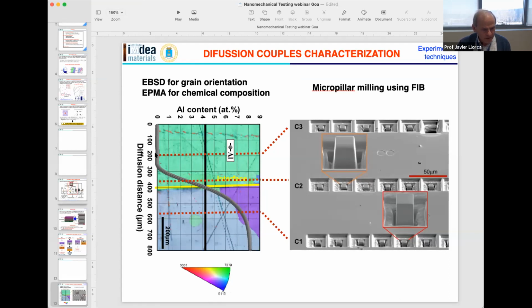And as you move from here to here, what you are doing is increasing the aluminum content. So at this point, the aluminum content is practically 0. This is pure magnesium. And as you move here, you are increasing the aluminum content up to 9%. If you carve micropillars along this line, you can see these nice micropillars produced by focused ion beam milling. This micropillar will have a magnesium content that is 100% and 0 aluminum. This micropillar here will have a higher aluminum content, and these micropillars in between will have different aluminum contents. This is for a grain with a given orientation.